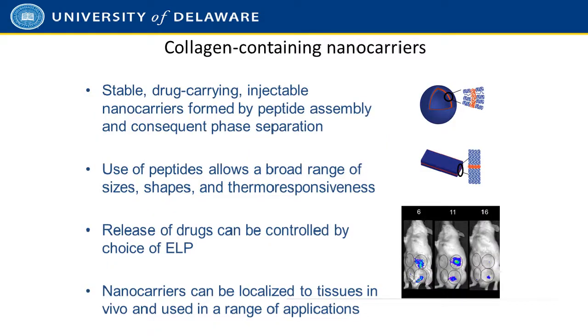So that was a really quick summary of some of our collagen-containing nanocarriers. We're able to make particles that are not just spherical like the ones I've shown you, but also ones that are platelet in structure, with a wide range of different diameters from 80 to 250 nanometers in the case of the nanoparticles, and then platelets that can have dimensions on the hundreds of nanometer scale. The use of peptides allows us to control their structure, so we can get a huge range of sizes, shapes, and thermo-responsive behaviors.